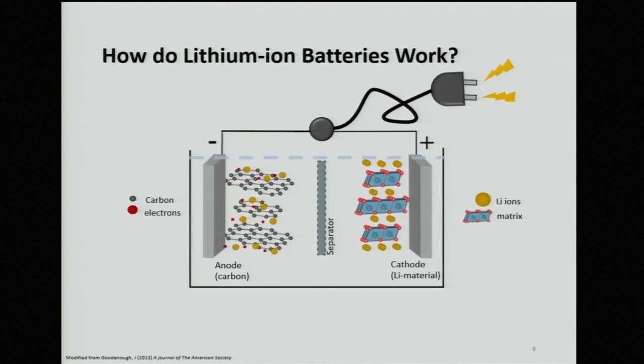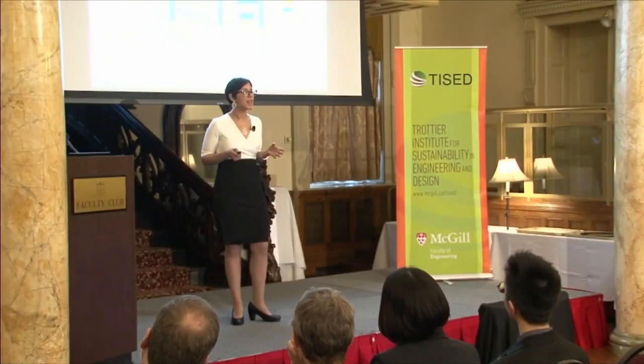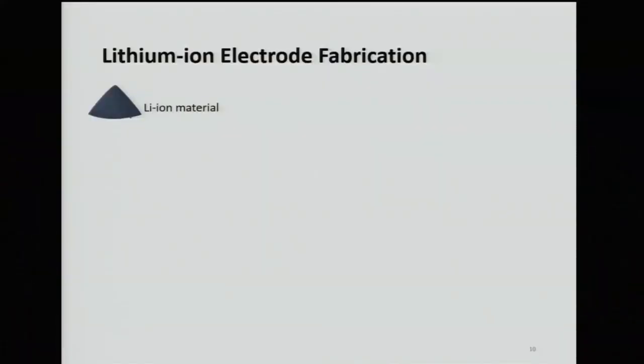Now, remember how I said that the electrodes are composed of coatings? Let's look at how we make a lithium-ion electrode coating. The first material we put in there is the lithium-ion material. Now, these materials tend to have really poor conductivity. So we can improve this by adding conductive material. And this is typically done by adding a small amount of carbon. We also add a binder to hold everything together.